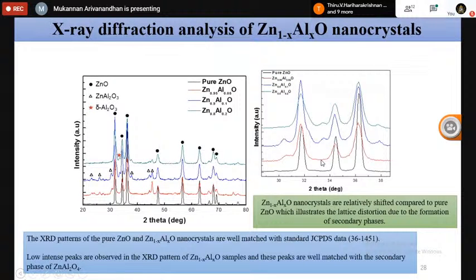Okay, and look at the X-ray diffraction pattern. So some interesting features have been observed. The first sample is a pure sample. The pure sample shows the wurtzite structure of zinc oxide, and when the aluminum content increased in the system, a secondary phase of zinc aluminate was obtained. This is also a semiconductor phase, and when the aluminum content increased further, the alumina phase was also obtained.